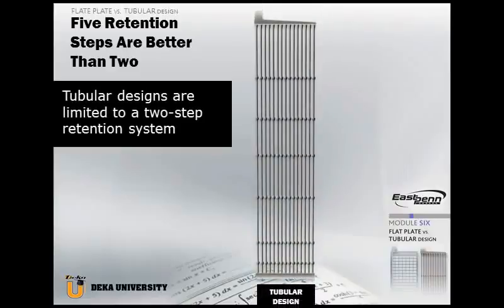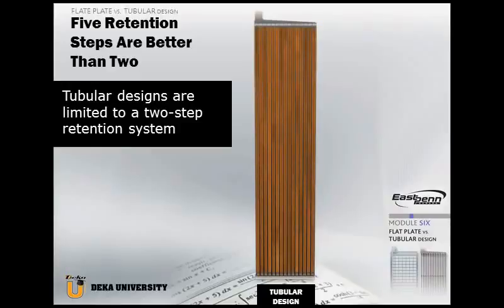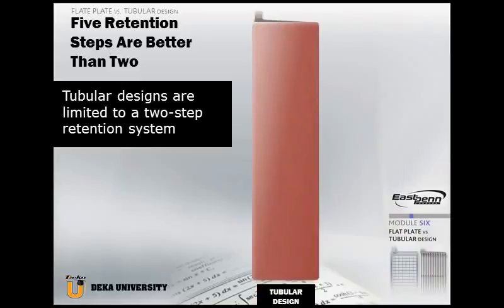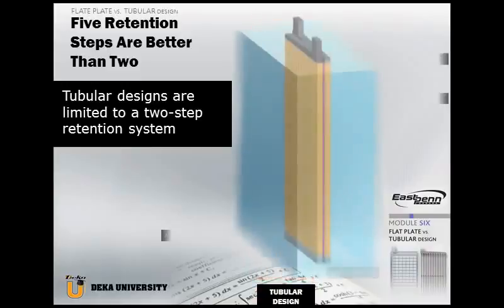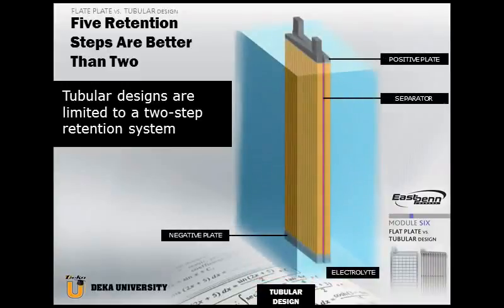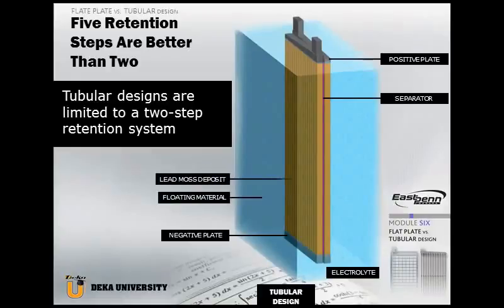Tubular designs are limited to a two-step retention system, which consists of a gauntlet or tube of polyester fabric and a separator. Using only two methods for retention, a tubular construction is prone to more active material shedding. Loose active material floating free in the electrolyte can settle on the negative plate to create a spongy lead moss deposit, which could potentially cause a short between positive and negative plates, leading to premature battery failure.